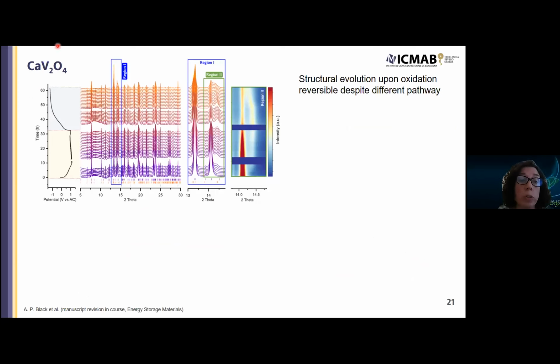Again, this is calcium V2O4. This is operando diffraction data at ALBA. We see again evolution upon oxidation, but in this case, upon reduction, we do also see an evolution of the X-ray diffraction pattern, despite the pathway seeming to be different. And this is something which we are still investigating.